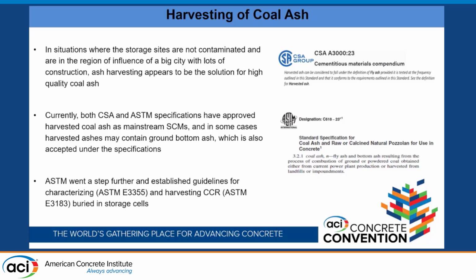So in situations where these storage sites are not contaminated with FGD, and also are in the sphere of influence of big cities where the demand is high, harvesting is a solution. Currently, both CSA and ASTM specifications have approved harvested ash as a mainstream supplementary cementitious material. And in some cases, harvested ashes do contain ground bottom ash. ASTM went a step further and established guidelines for characterizing the CCR in the landfill and also harvesting it.